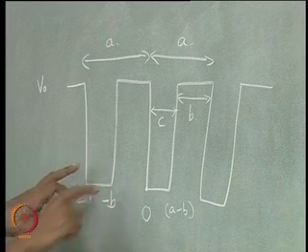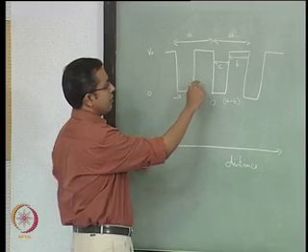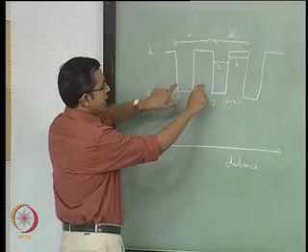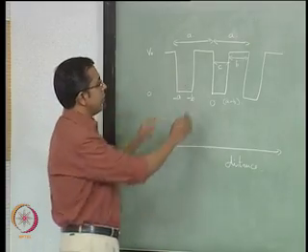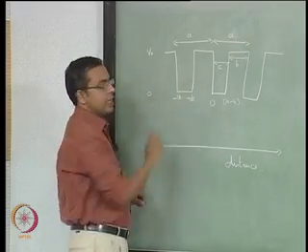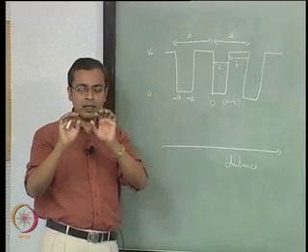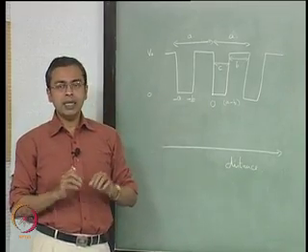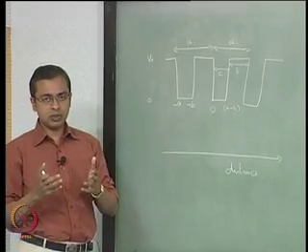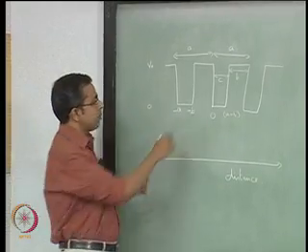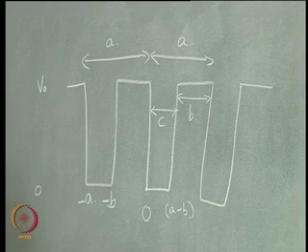What we are going to do is solve the Schrodinger wave equation where V equals V naught, and solve it where V equals 0, and we are going to require that at the boundary these two solutions give us the same value. This is based on our general understanding that the solutions we get have to be reasonable, which implies that they are going to be continuous.